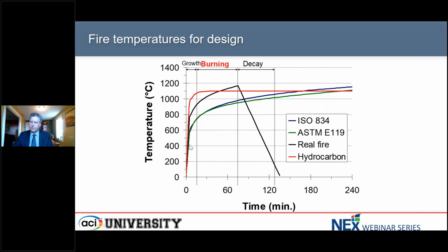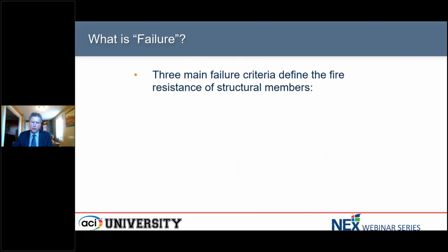However, for most standard fire tests for determining fire resistance, we're using these lower two curves, either the ISO or the ASTM. And so that is fairly standardized, but I think it's important to recognize that that doesn't necessarily represent what's actually going to behave in a fire. But those time temperature curves have been used for over 100 years now, and we have a good experience for them. There are some uncertainties when we change some of the conditions under which they're used, but generally it's fairly reasonable.